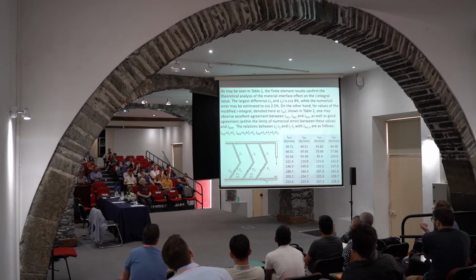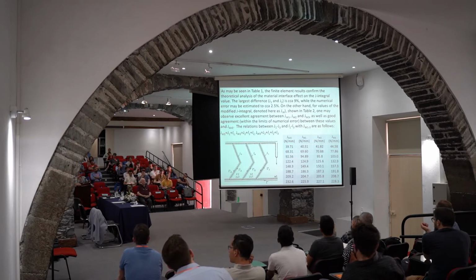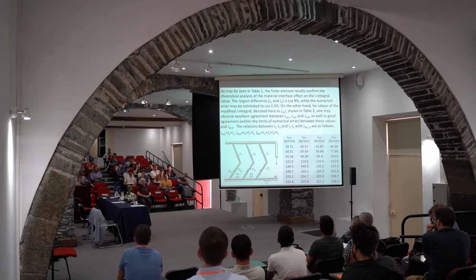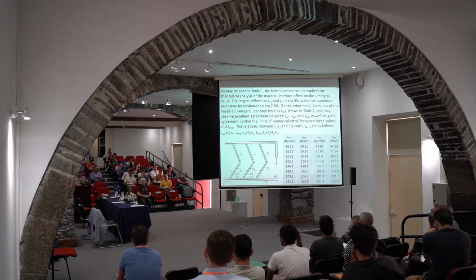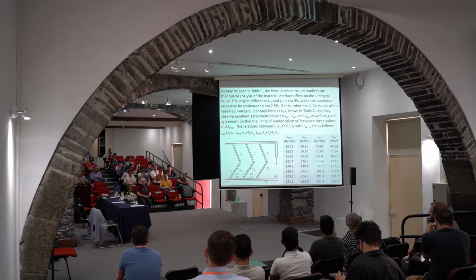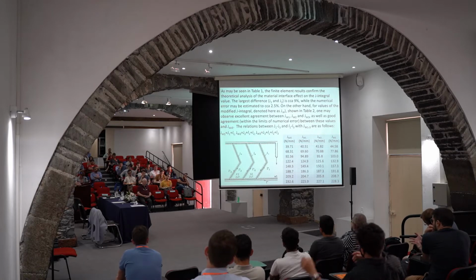So, in this way, we proved 2 things. Of course, theory was right. It is sound theory. There is a difference. There is an error if we just measure the integral of this outer path. But on the other hand, from an engineering point of view, from a practical point of view, it's not a big deal. It's less than 9% in this case. And it is so for all welded joints which do not have a big difference between their regions, between weld metal, base metal, and heat affected zone.